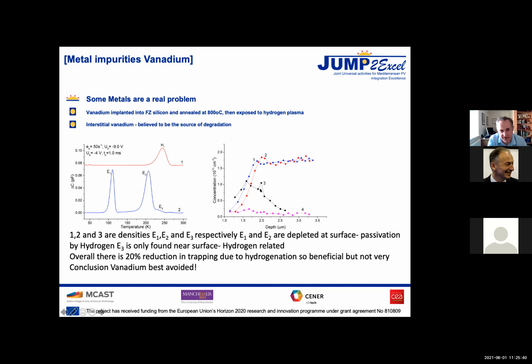Vanadium is very effectively passivated by hydrogen. So our conclusion from this, and we published it about 3 years ago now, was that vanadium is a really damaging metal, and if you try and avoid that from your feedstock, you'll be better off.